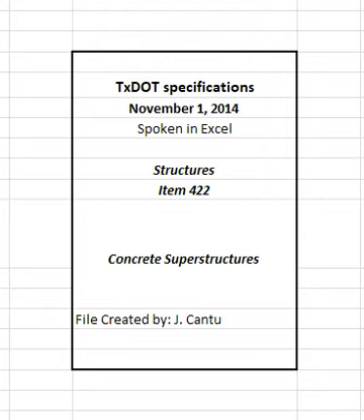Move transverse screeds longitudinally approximately 1/5 of the drum length for each complete out and back pass of the carriage. Screed the surface of the concrete enough times and at intervals to produce a uniform surface true to grade and free of voids. Fog unformed surfaces of slab concrete in bridge slabs and in top slabs of direct traffic culverts from the time of initial strike-off of the concrete until finishing is completed and required interim curing is in place.